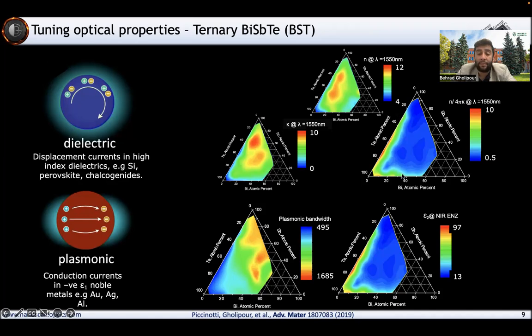So you can clearly identify that closer to the binary compositions, you've got a much better figure of merit here. So these binary compositions are very good for the telecom band, and these ternary compositions are much better for photovoltaic applications. So computing is in the binary, and photovoltaic seems to be more akin to the ternary side of things. And if you look at the plasmonic properties, you can see again that the plasmonic compositions are generally the ternary compositions, much heavier on the bismuth side of things. So the metallic component increasing in that alloy gives you a much more plasmonic response, and a huge plasmonic window variation that we can tune across by just changing the composition of the alloy.